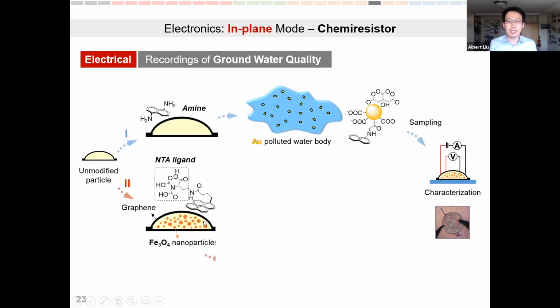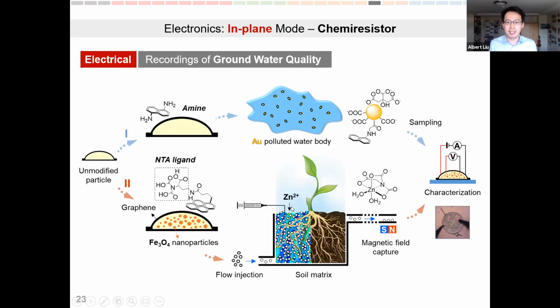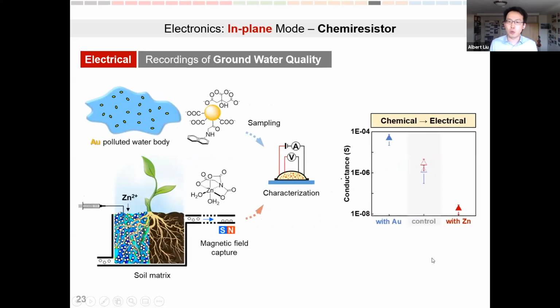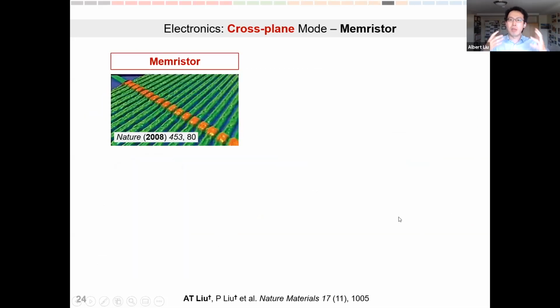Alternatively, you could functionalize the graphene surface with something called an NTA ligand, or nitrilotriacetic acid ligand, and then use it as a zinc cation sensor, because the NTA ligand chelates onto zinc cations, and these particles can be injected into a soil matrix, and after they travel through the soil matrix, we can harvest these microparticles and again query them for surface electrical conductivity. Long story short, we can get a very selective and sensitive sensor to turn chemical signals into electrical conductivity measurements. What about memory, digital memory?